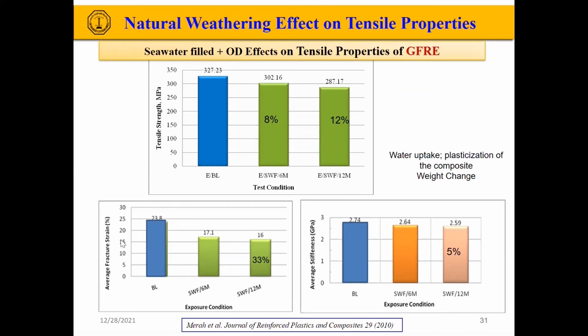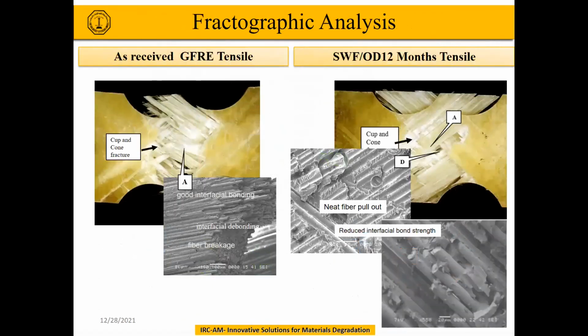The average fracture strain reduced even further. You can see that after 12 months, we have about 33% reduction. But the average stiffness did not reduce much after 12 months of seawater filled and outdoor exposure. We looked at the fractured surfaces, and we have observed this is the as received glass fiber reinforced epoxy pipe.